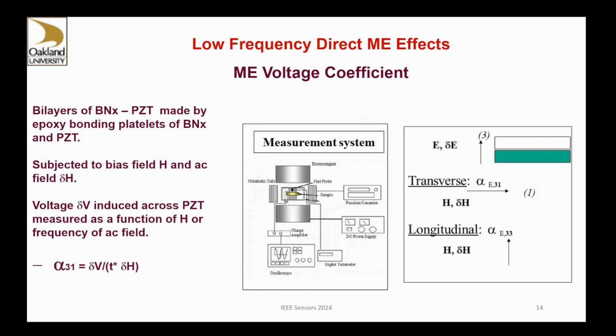One is where all the magnetic fields, both AC and DC, are in plane, and the PZT was poled perpendicular to the plane. The voltage was measured across the PZT. The PZT that we got was from vendors with silver electrodes on them and pre-poled, so all we need to do is just make a composite. The other was what we call longitudinal. In this case, both AC and DC magnetic fields are perpendicular to the plane, but also the PZT was poled out of plane.